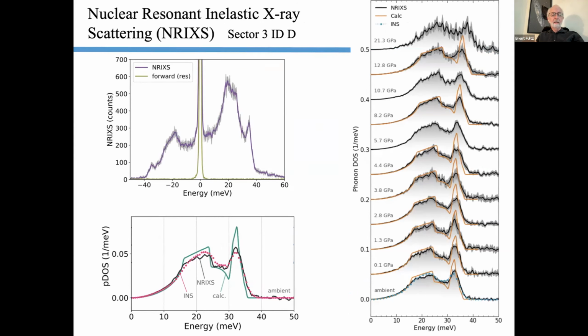We had actually done some inelastic neutron scattering on this, and that gave us this dotted red curve here. And the NRIXS has got the black curve, similar resolutions actually, amazingly. But generally the weight is the same. There's no different weighting where the nickel atoms are contributing to a different part of the DOS. And this had been studied also with other iron-nickel alloys by a former student, and it looks like the partial DOSes of the nickel and the iron are the same. That makes the entropy interpretation a lot easier.